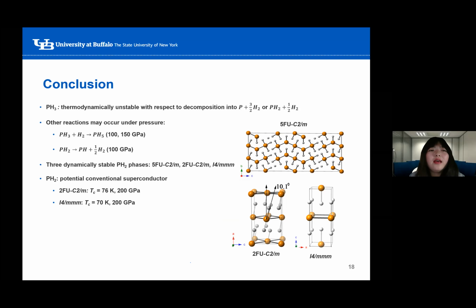So as a conclusion, the classical stoichiometry of PH3 at higher pressure is thermodynamically unstable with respect to decomposition into the elemental phases or PH2 and hydrogen. There are other reactions that may occur under pressure, including the formation of PH5 and PH2 decomposing into PH and hydrogen. We identified three dynamically stable PH2 phases that we discussed in this section. And we found that the two PH2 structures with calculated Tc of 76 and 70 K at 200 GPa would be good candidates for the measured superconductivity.